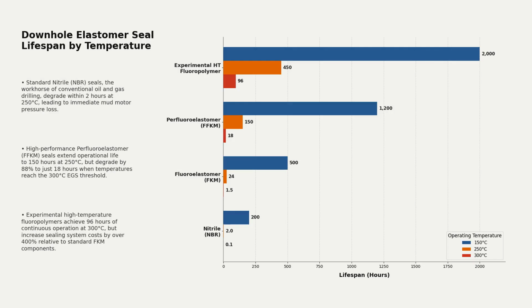Thermal degradation is not limited to electronics. Downhole sealing systems face immediate mechanical failure under extreme thermal stress. Standard nitrile seals, the baseline for conventional oil and gas wells, degrade within 2 hours at 250 degrees Celsius. This degradation causes rapid pressure loss in mud motors, forcing operators to pull the entire drill string.